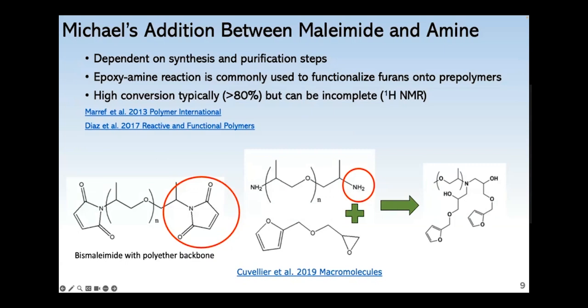Another likely side reaction is this Michael addition between maleimides and amines. One of the most common ways of attaching furans onto a prepolymer backbone is through an example reaction like this. So this epoxy group will react with amines. And epoxy amine reactions tend to be high conversion, but some authors who used similar DA synthesis schemes used HNMR and found that the epoxy amine reaction was incomplete for their system, sometimes ranging from 80 to up to 95%. And then those free amines can react with maleimides at temperatures as low as 75 C.